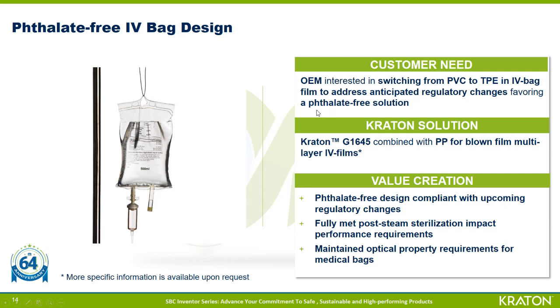One of the Kraton solutions is to use G1645 polymer, which is blended with polypropylene. And films from such a compound can be made using either a cast film extrusion or a multi-layer blown film extrusion process. The value that the customer sees from this Kraton solution is that the IV films are then phthalate and plasticizer free, and they can meet the mechanical and optical property requirements very well before and after sterilization.